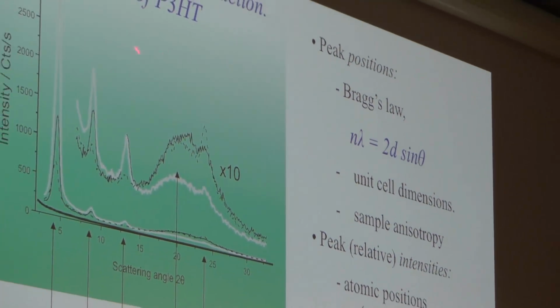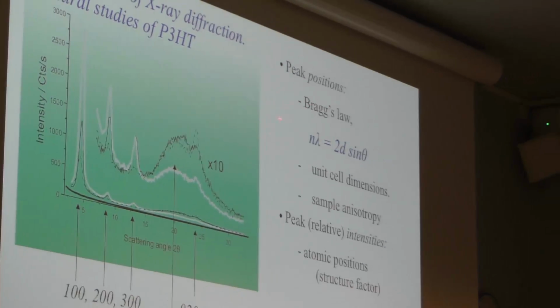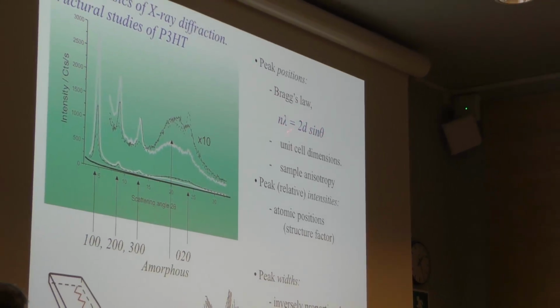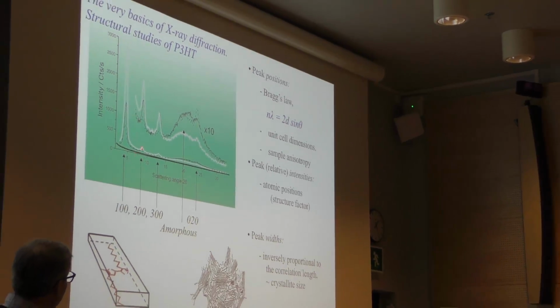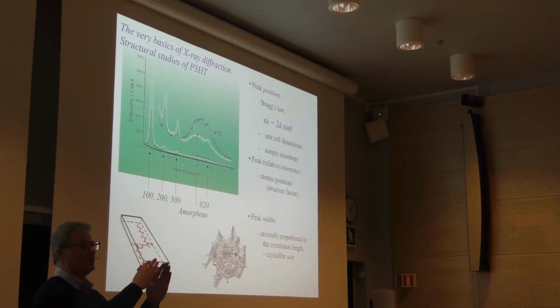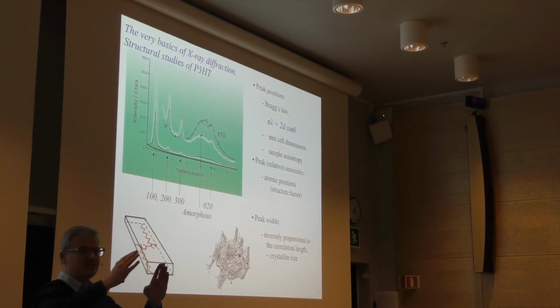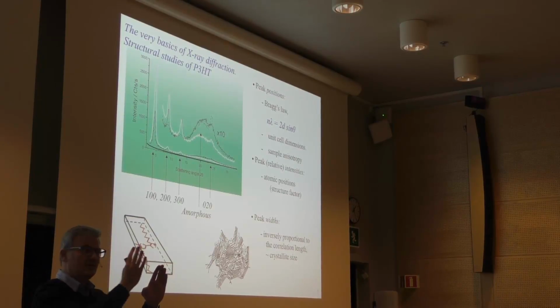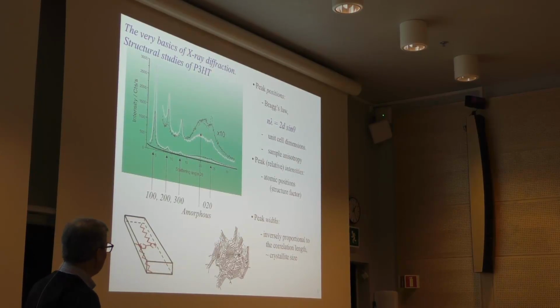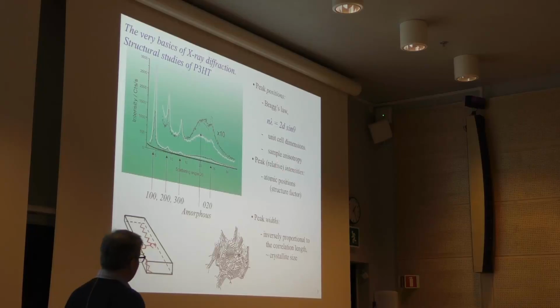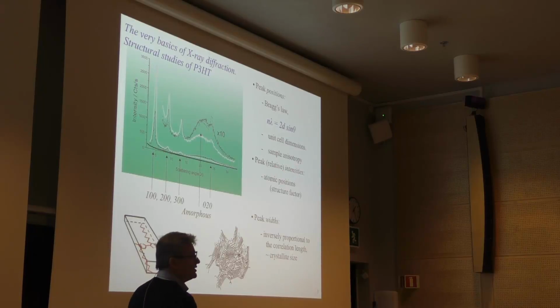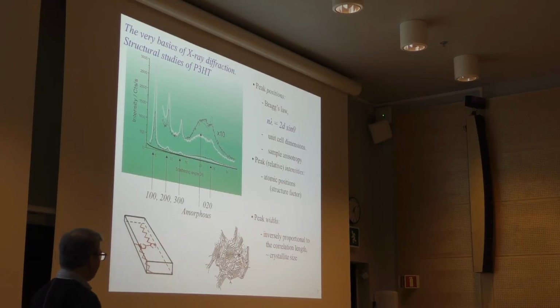And some of the very basics of X-ray diffraction that most of you presumably know is that via Bragg's law we can calculate these positions. We can use this to learn about intermolecular distances that are periodic inside of crystalline assemblies. From the peak intensities we can learn about the atomic positions, and from the peak widths we can say something about crystallite sizes. So that's the very basics.